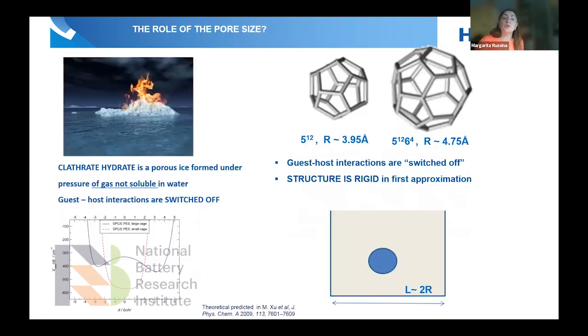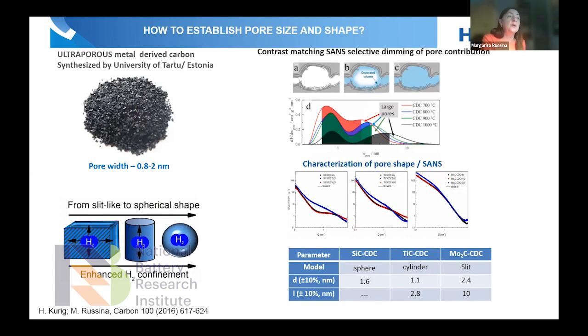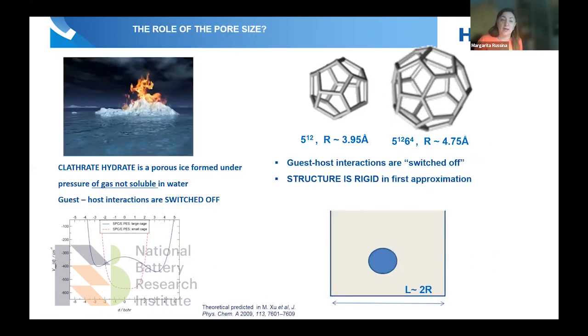Once you establish this pore size, you want to know what is actually happening in the pore itself: how the ions and molecules are moving inside the cages. This is, of course, a very complex question, because you can switch on the guest-host interaction, and this depends on the chemistry of your system. But what is the really geometrical impact? For this purpose, we took a particular system which consists of porous ice, and placed hydrogen in there. This porous ice creates two cages.